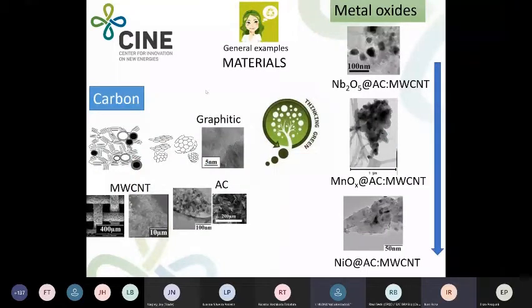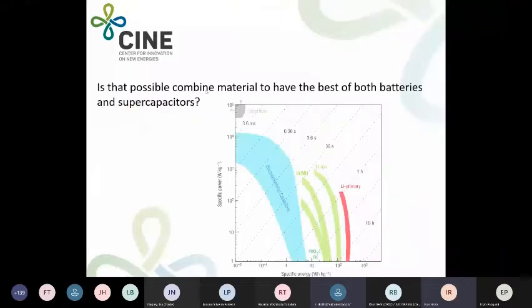The materials we work with here at Unicamp are mostly activated carbon for the positive electrode, which we produce by biomass carbonization. We make a char, and then we activate it with CO2 or water, so in a very simple and cost-effective way. We also use graphite and treat it to make graphene and this kind of material, combined with more noble materials like nanotubes, which we produce here from ethanol, which is cheaper as well. So we combine this kind of material in a negative electrode, for example, with niobium pentoxide, with manganese or nickel oxide as well, to bring Faradaic reactions to the system in a very peculiar way.